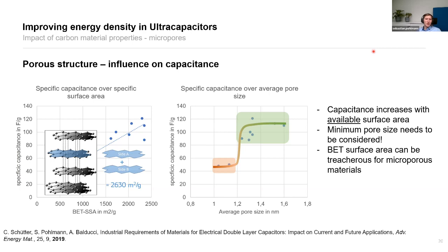One thing that I always want to mention when I mention BET surface area is that you still see today a lot of publications where you have BET surface areas larger than 2,600 square meters per gram. If you ever measure this, then I would always ask you to not publish it, because it is a nonsensical value in the sense that 2,630 square meters per gram is the maximum of any carbon material that you can have.